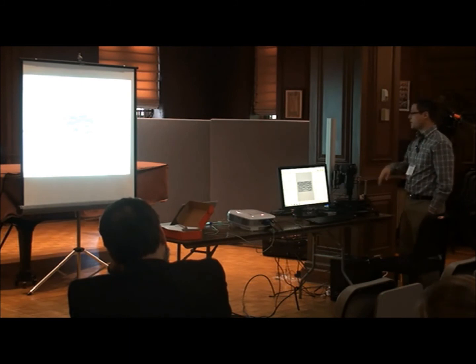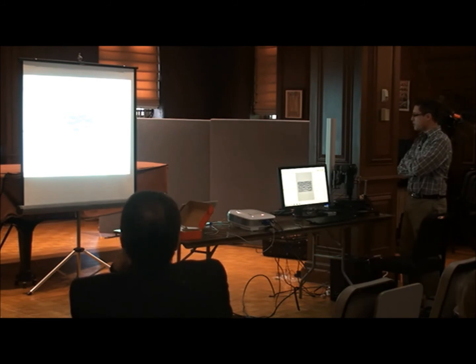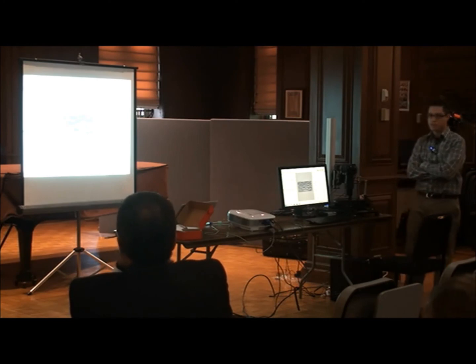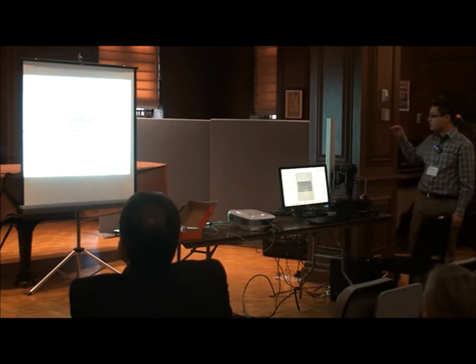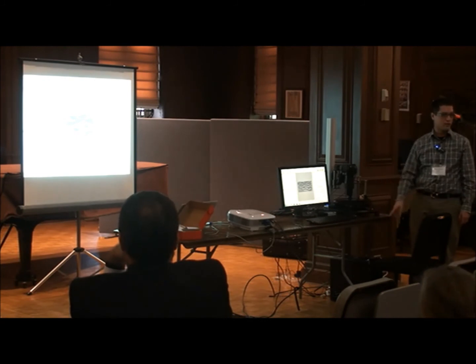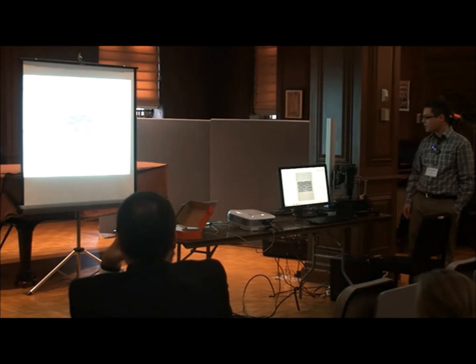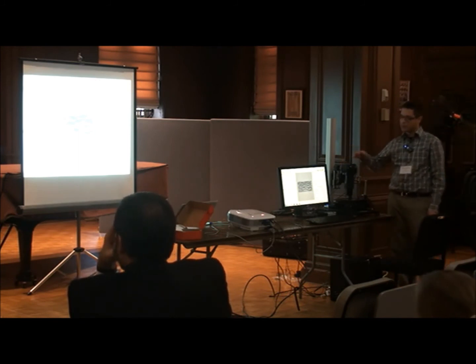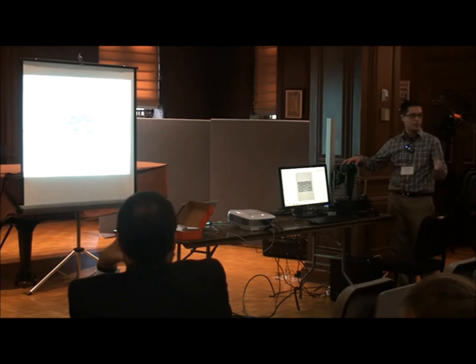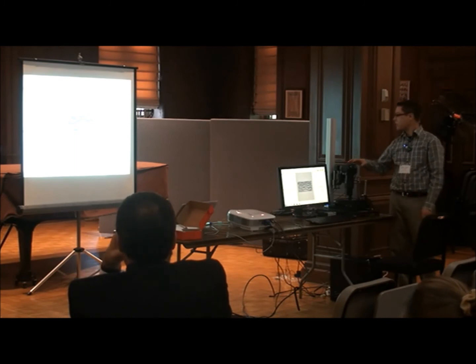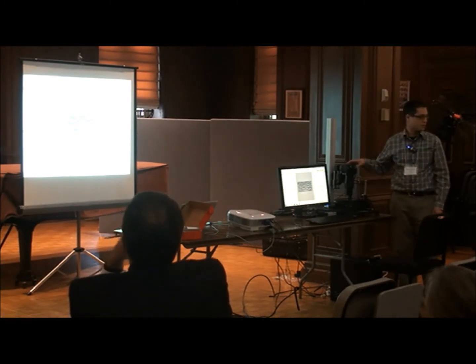Load it from file. So a couple steps when it runs. It has to do the calibration. If it hasn't done the calibration yet, then it takes a number of seconds to build the calibration map. It's integrating the surface normals now. That takes some amount of time because it is 18 megapixels. It took 20 seconds to solve for all the surface normals. Integration phase took 5 seconds. Saving the file took 0.1 seconds. So we can process the 18 megapixel scan in about 30 seconds on this hardware. It can be faster on an even more powerful computer. To capture the images, it's about 12 seconds, maybe 1 second exposure, some time between the images, 6 images. So in less than a minute, we've done an 18 megapixel surface measurement.